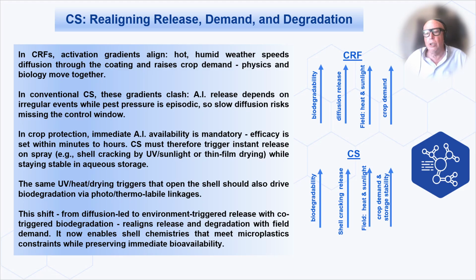And here's the opportunity. Those same triggers that open the shell, UV, heat, drying, can also drive biodegradation if we design the shell with photo and thermolabile linkages. This is the shift from diffusion-led release to environment-triggered release with co-triggered biodegradation. That realigns release and degradation with field demand. It gives us shells that no longer leave behind microplastics, but still deliver immediate bioavailability when it's needed most. So the new paradigm is simple. Release, demand, and degradation finally working together instead of against each other.